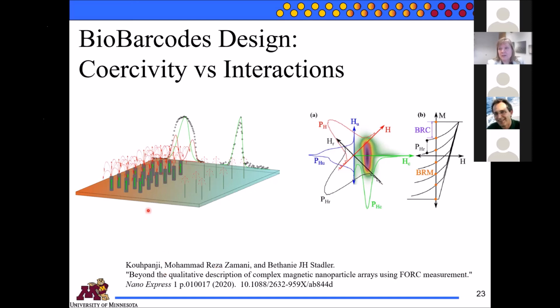And what he's going to play with is the coercivity, which in particular comes from the diameter of the nanowires and the separation of the nanowires. By playing with that coercivity and interaction field, can he dial in a specific code and find that code among others? Our first thought was to use something like FORC, first order reversal curves. In that case, you saturate a sample, then you jump to a reversal field, and then sweep back as you measure. Jump to another reversal field and measure as you sweep back to positive saturation, and so on. You just keep generating this family of curves.